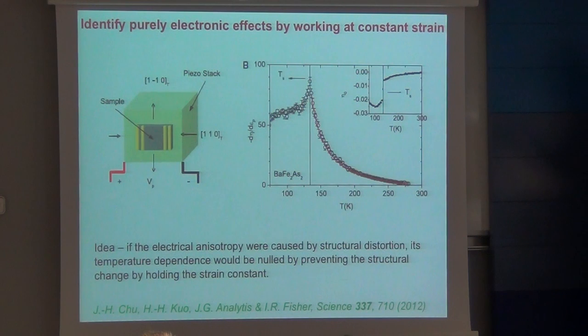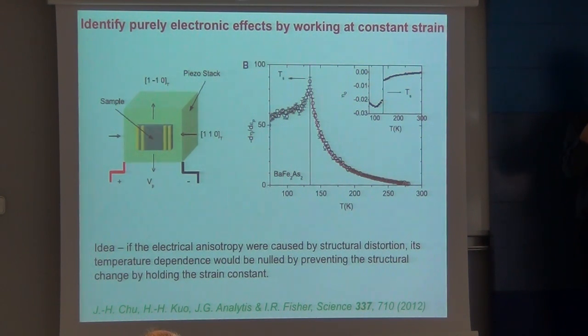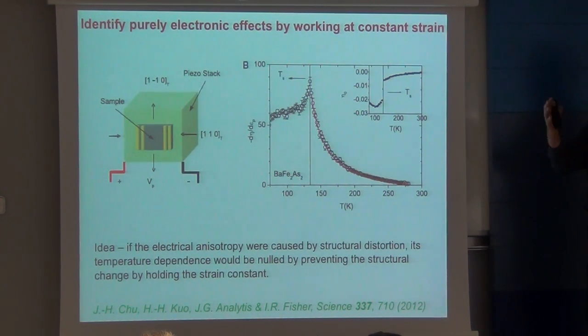So we're going to try and keep the lattice constant of this sample constant as we lower the temperature, and we're going to see what the resistive response is as we do that. And the idea there is very simple. If it's structurally driven and you've suppressed the ability of the structure to change as you change the temperature, then you shouldn't see any change of the anisotropy or the tendency to anisotropy as you change the temperature. If, on the other hand, the anisotropy is fundamentally coming from the electronic system, it shouldn't care.